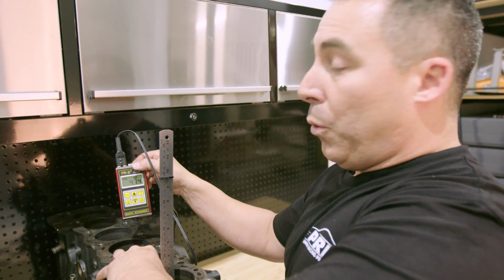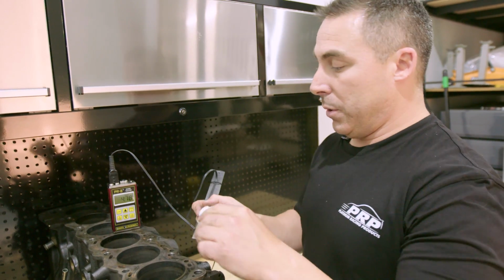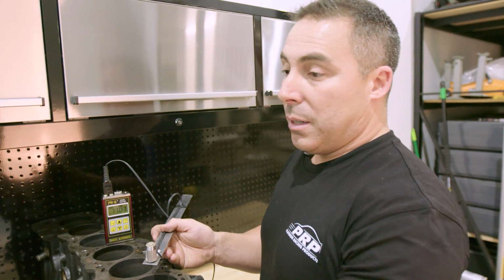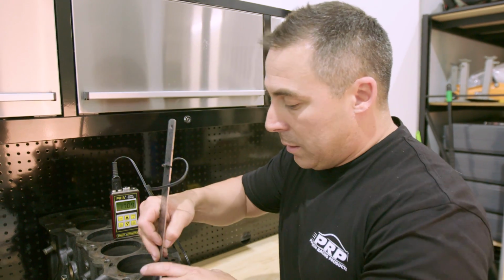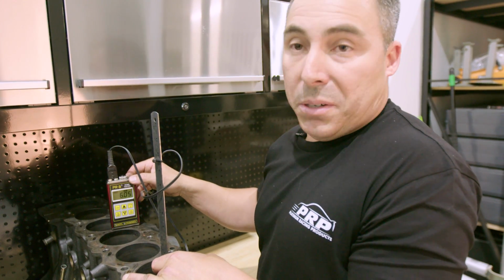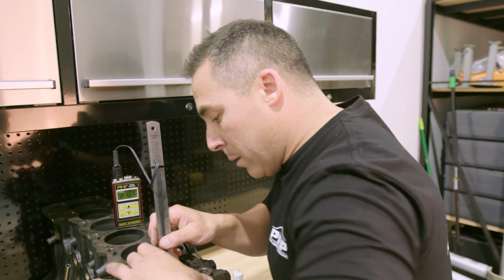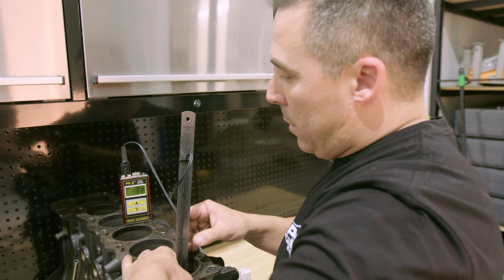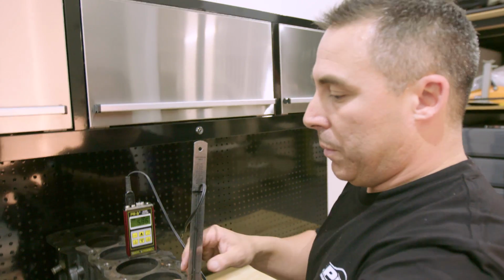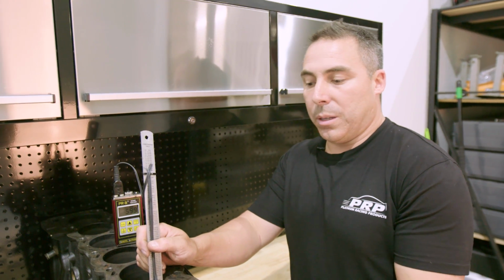Okay, so that's around 4 mil after we take that first cut to an 86.5 bore. So pretty average. I mean, it's probably a millimetre, half a mil under some of those other ones. Nothing special, yeah? 6 mil, take 0.75 off. We're still around average in the 5s. Okay, 5.8. We're back down to around the 5 mil after we take that oversized cut out. So there's not that much different with an RD28.